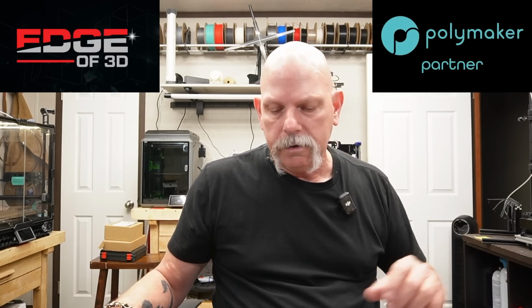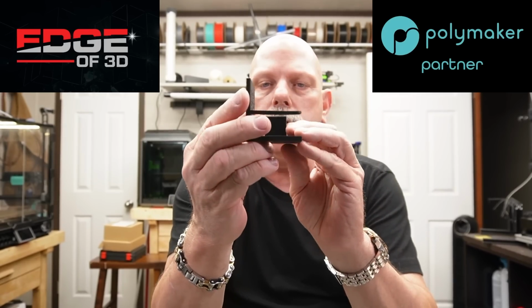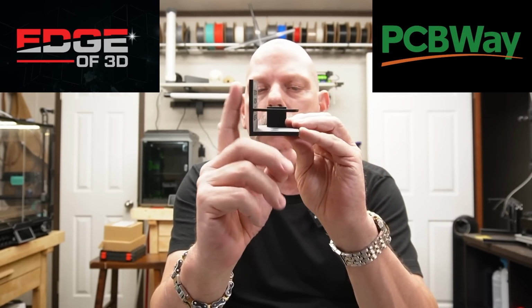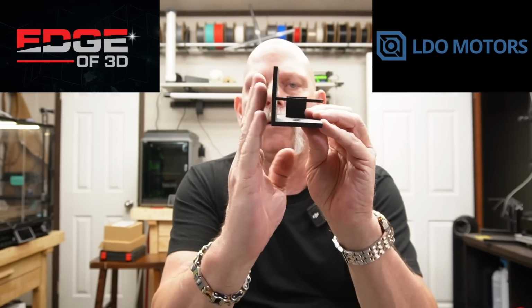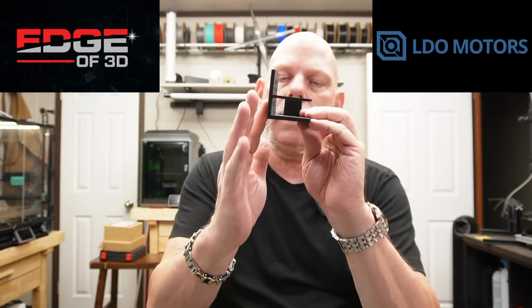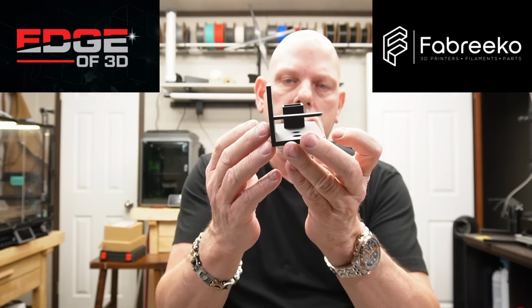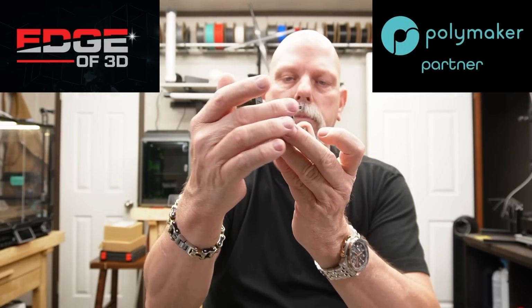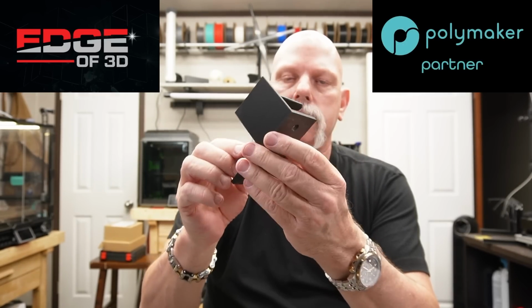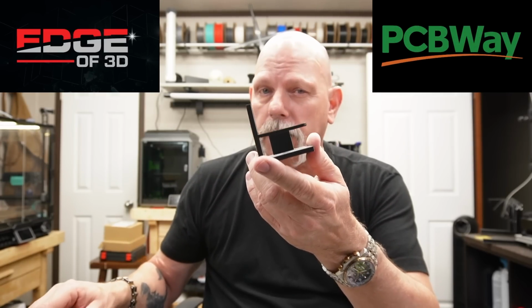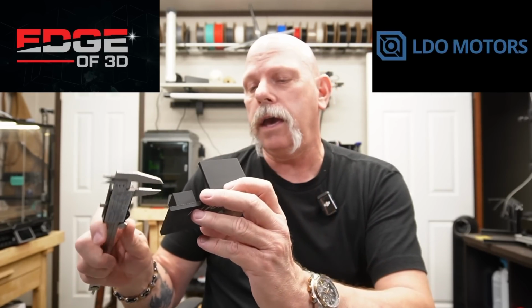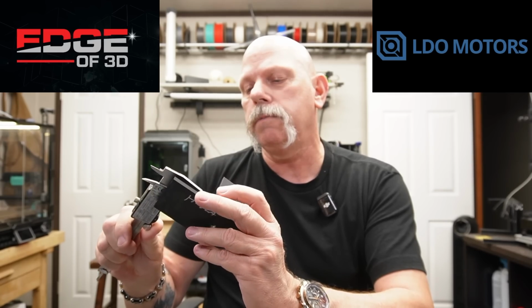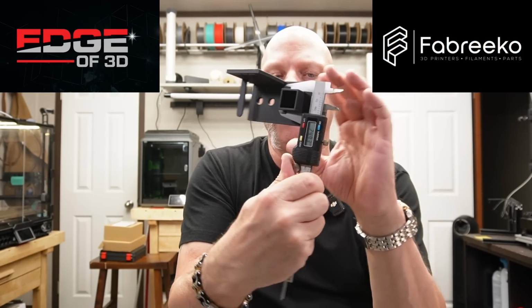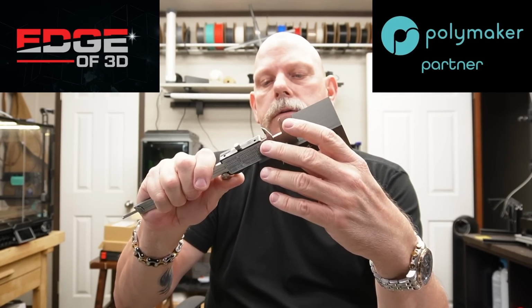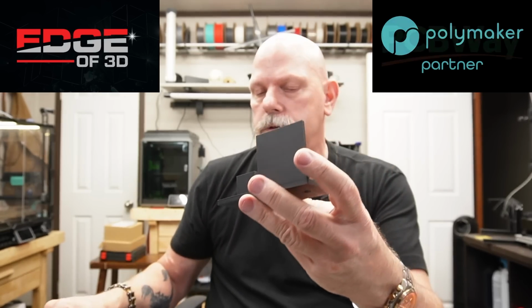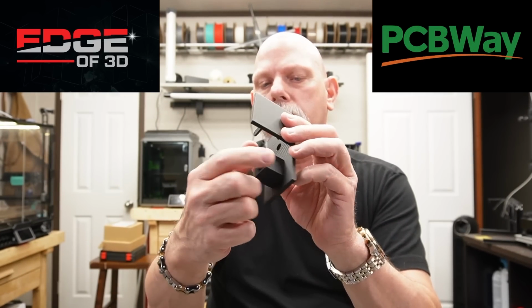And finally, the heat-treated PLA. Now, if you really look at this close, and I go get an engineer's right angle, there is some curvature to this back now. But it was in there at 150 degrees. This is still parallel to this right here. So, all things considered, it held up pretty dang good. And as far as shrinkage goes, 24.94, 24.98. So negligible shrinkage on the parts.